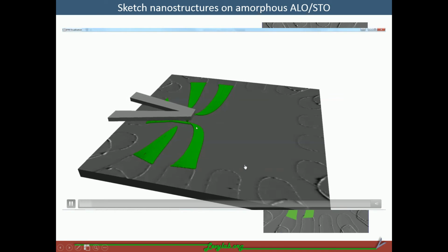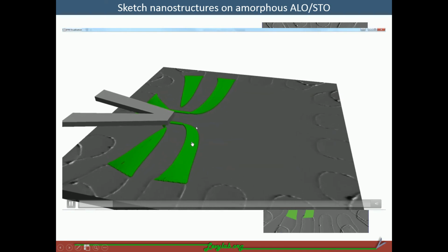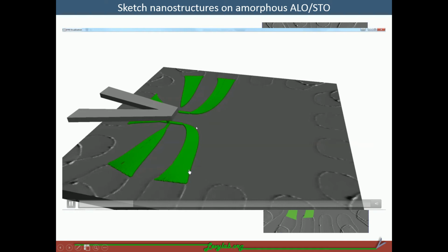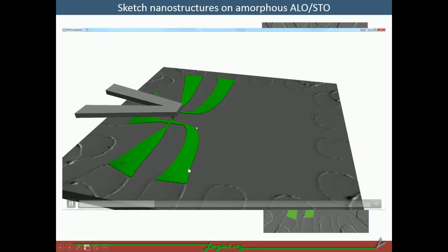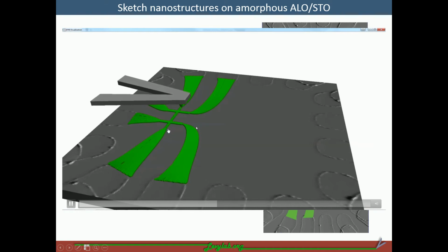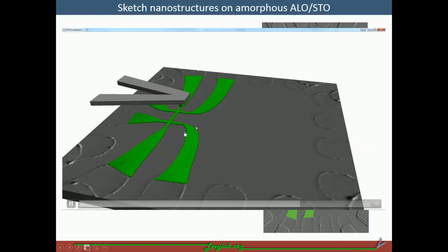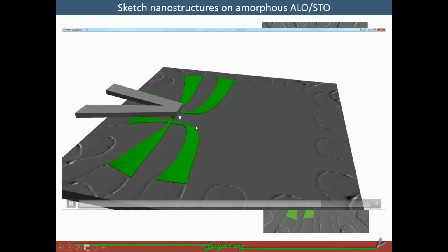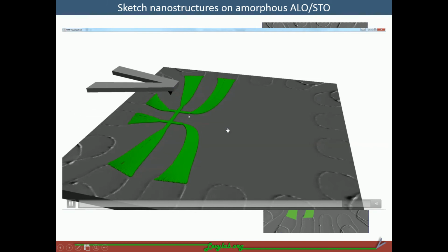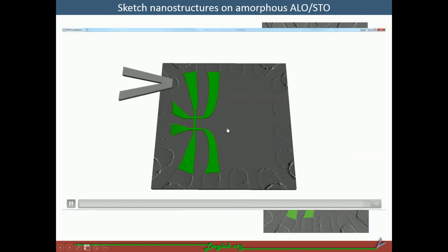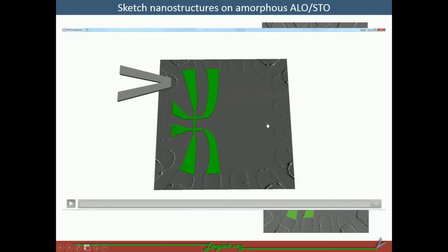Basically, we write those virtual electrodes first, which improves the contact between the structure and the metal electrodes, and then we write the structure in both directions. Here, the main channel we write horizontally first, and then we write vertically again, which improves the quality of our structure. Here the channel width is about 500 nanometers, and the channel length is about 3 microns. So here is the whole image of the structure.